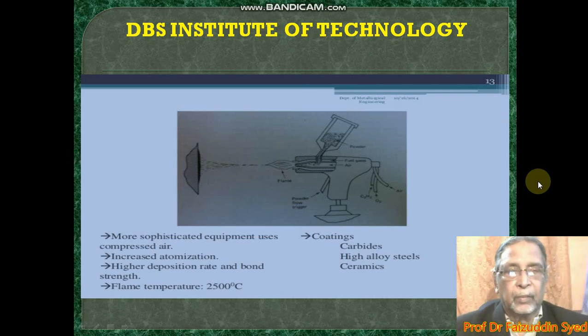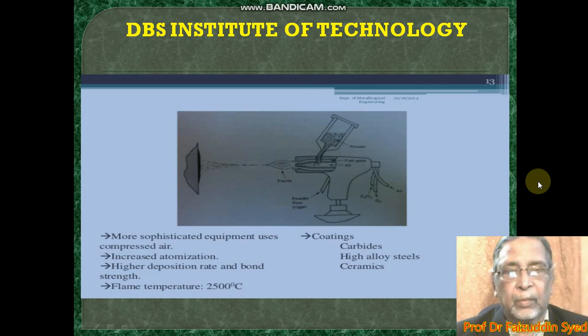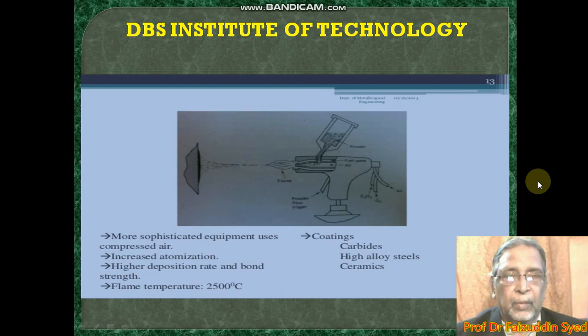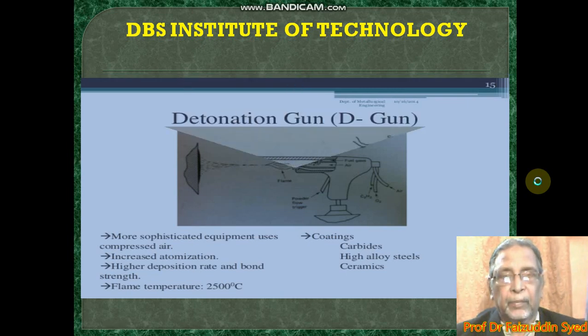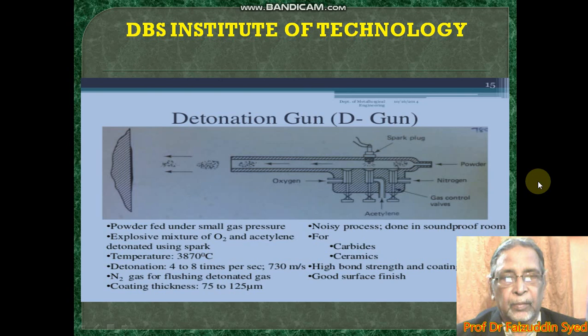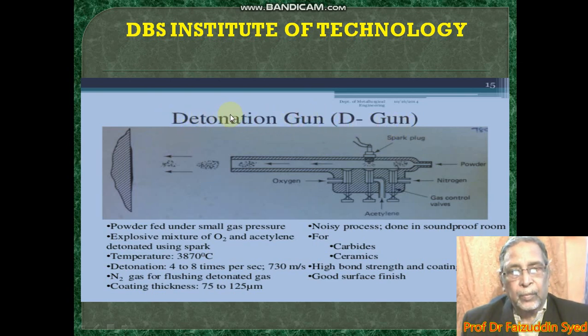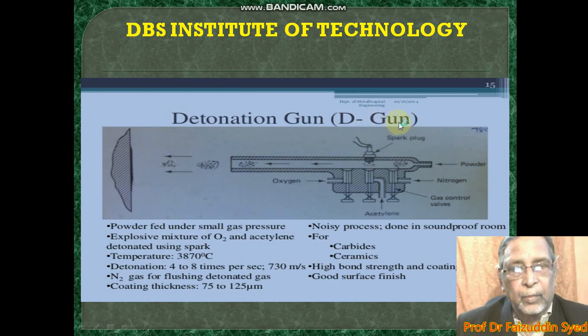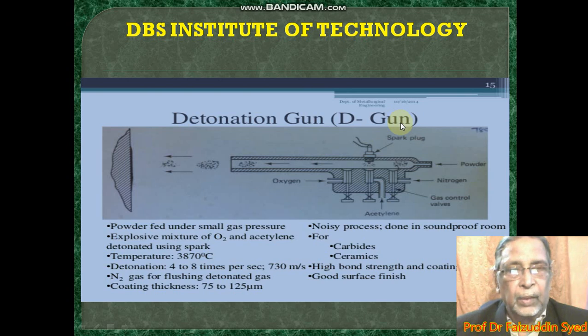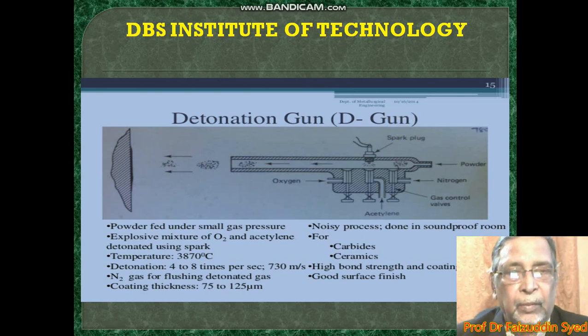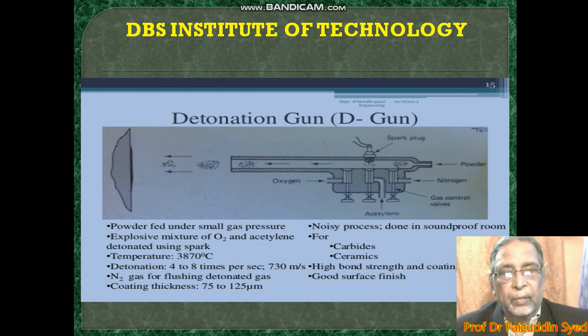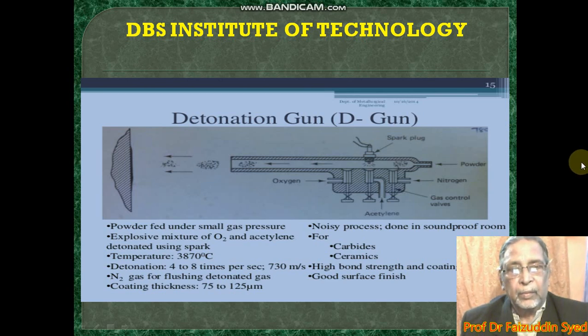What coatings can we do with this? We can make carbide coatings, high alloy steel coatings, ceramic coatings, and many others. Now you are seeing a special gun called the detonation gun, D gun. This gun is used for spraying carbides and ceramics. It gives a high bond strength and coating density with good surface finishes. But this process makes a lot of noise. You should do it in a soundproof room.